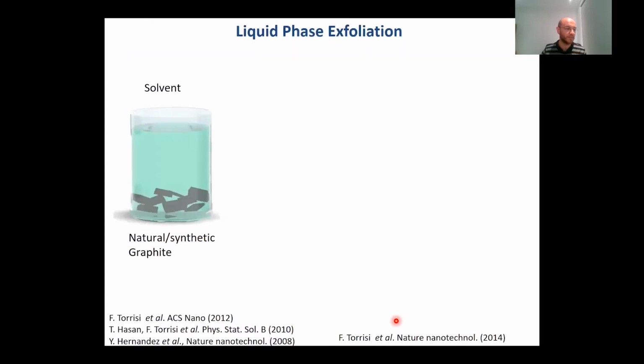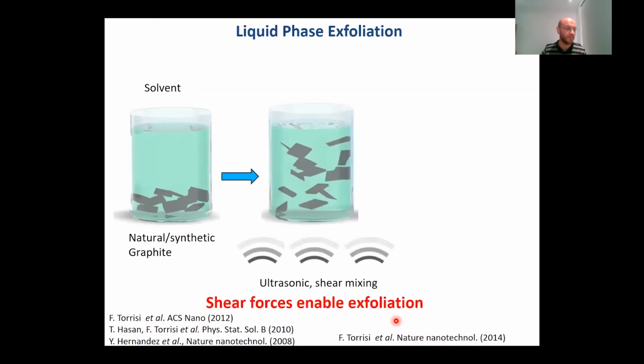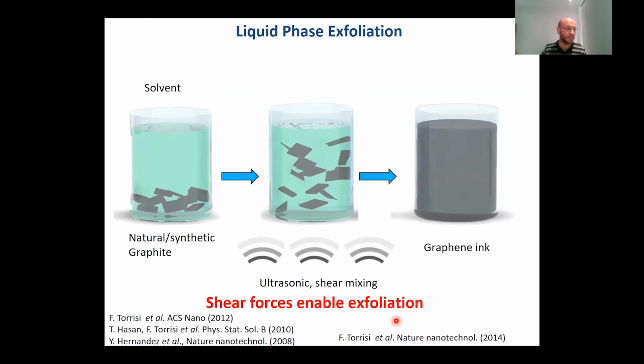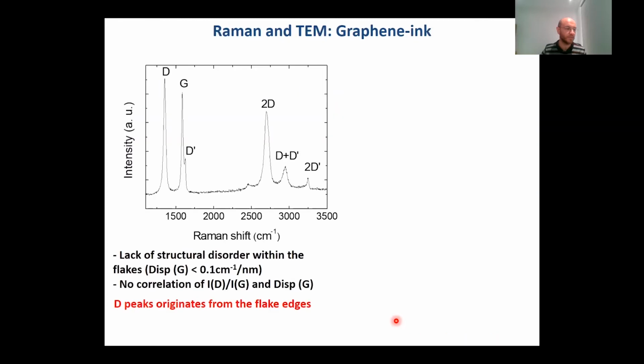So what we try to do is use liquid phase exfoliation, to exfoliate layered materials in solution via various types of shear forces, which I'm not going to thoroughly investigate and show you today. But with this, we can create dispersions of high quality 2D materials. Of course, we need to go from a standard dispersion into an ink if we want to develop printed electronics. So first of all, we check the quality of these flakes, and it's very well known that, for example, for graphene inks, shear exfoliation allows high crystallinity with low structural defects.